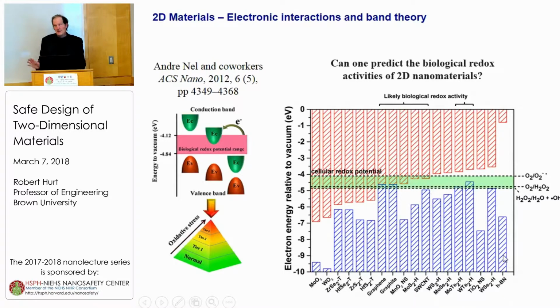And now this is a complicated field, but at some crude level, it certainly works, because if you look at hBN, it's a wide bandgap semiconductor. There's a huge gap here where there are no allowed electron energy levels, nothing that comes close to overlapping with the cellular redox range. And in fact, in most data, people do not see hBN as being redox active. You compare that to another common nanomaterial like molybdenum disulfide. And molybdenum disulfide, right here, its conduction band edge dips into this redox potential, and it would be predicted to accept and return electrons in biological systems. And the data I've seen do confirm that.